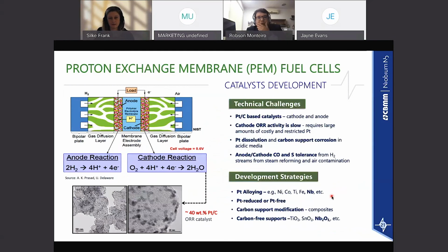When you look at the proton exchange membrane, what are the technical challenges? Hydrogen is the fuel. You have both sides of the proton exchange, cathode and anode, based on platinum. Platinum is the catalyst. Again, it's a costly material. One of the greatest technical challenges is in the cathode reaction, the so-called oxygen reduction reaction. The activity is quite slow. The kinetics is very sluggish, and we require quite a bit of platinum, which is a costly material. So we need at least to improve the cathode reaction with better utilization of platinum or new materials that make it even faster in terms of kinetics.